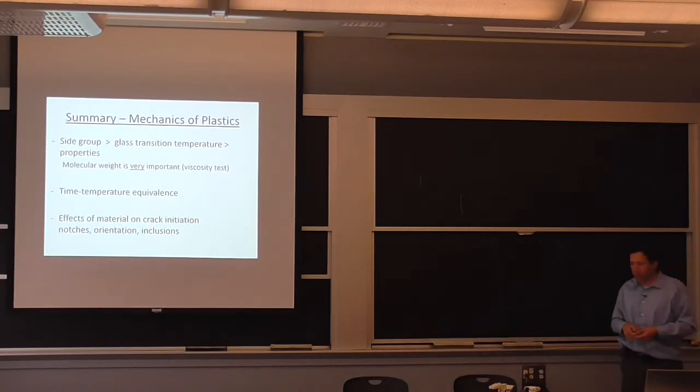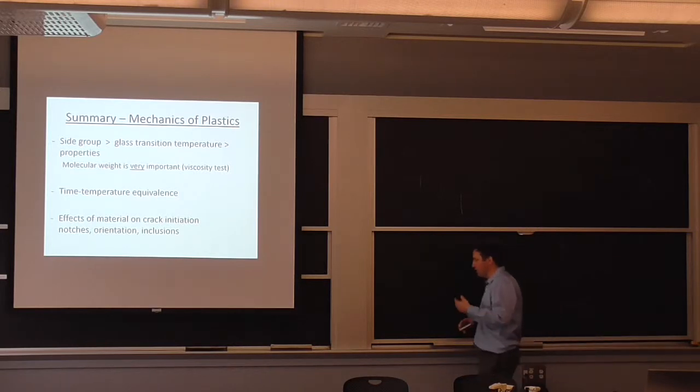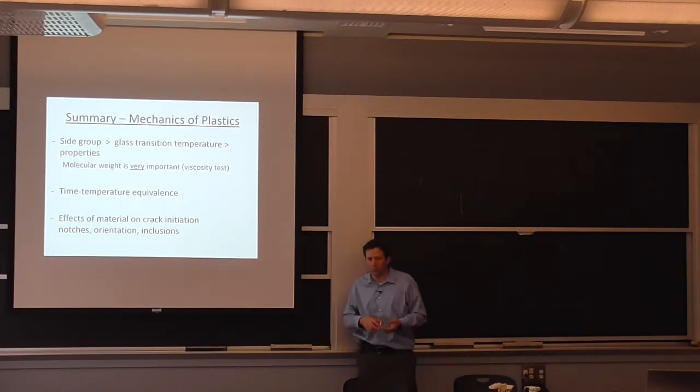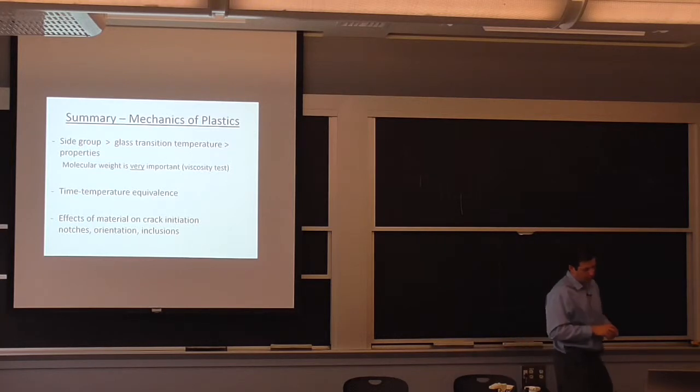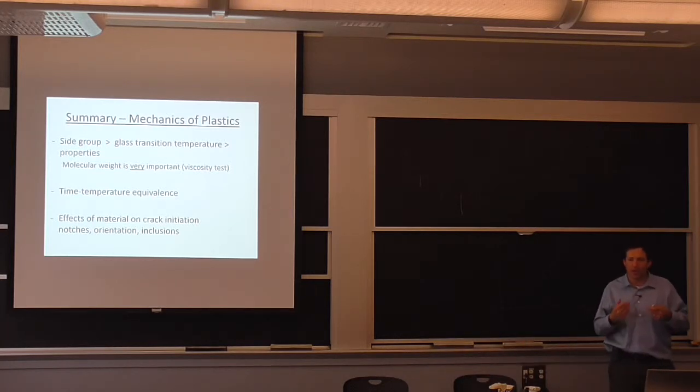The time temperature equivalence, you can use it to a different extent depending on what you're trying to do. If all you're trying to do is to model the overall bulk deformation, you can use it extensively. If you're trying to look at what actually is going to cause cracks, then you're more limited.